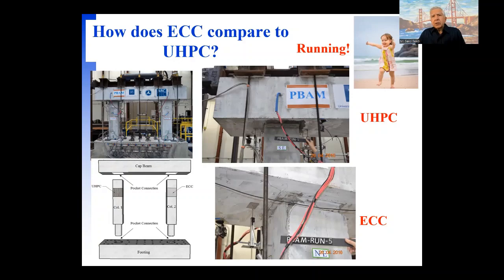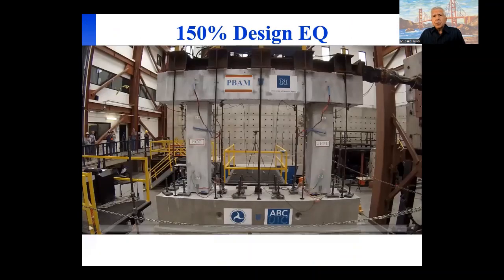The much higher strength of UHPC actually forced the damage somewhere else in the structure. So this is one of those rare cases where the more is not the better. In other words, the higher strength of UHPC was not beneficial. Now I'm going to show you a video clip of that last test.